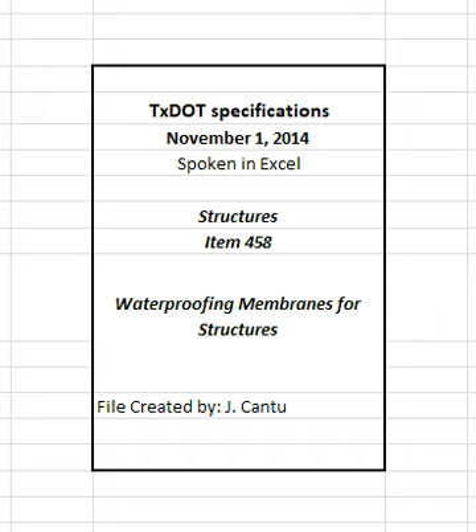Store asphalt planks, asphalt mats, and asphaltic panels in a manner that will prevent warping and breaking. Provide a wood float finish to concrete decks and other unformed concrete surfaces to be waterproofed. Cure concrete surfaces to be waterproofed for at least 7 days before applying waterproofing, or as directed by the waterproofing materials manufacturers. Ensure steel or concrete deck surfaces to be waterproofed are clean, dry, smooth, and free of fins, sharp edges, and loose material. Use grinders, if necessary, to remove protrusions that would puncture waterproofing membrane.